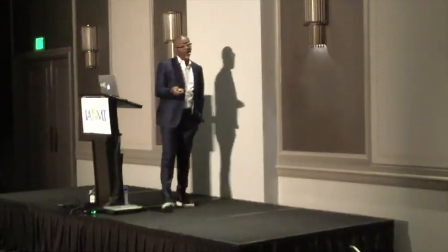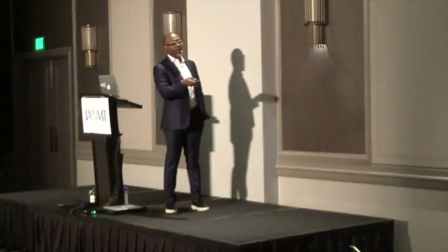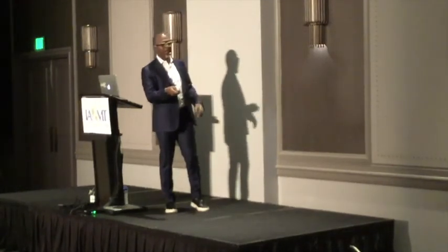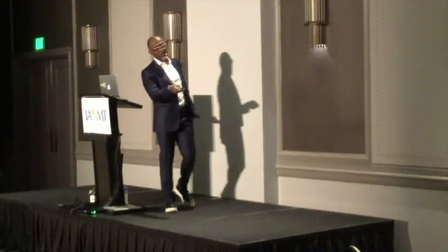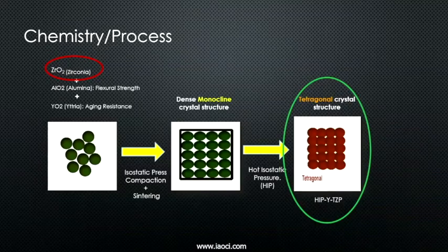So again, now when the implants are made, you take all these materials, you put them together, then you compact them, then you sinter and further compress them, and then you get, in this case, hot isostatic press zirconia. Okay, so it's always a combination, like I said, to obtain what you need.